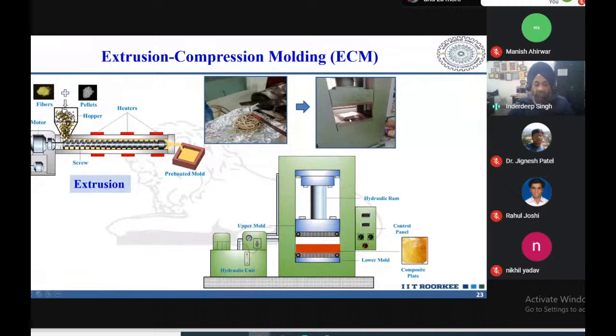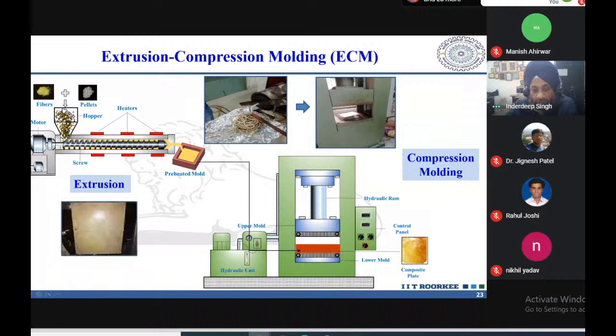So we have designed a mold which can give us a composite plate of 30 centimeters by 30 centimeters, or 300 millimeters by 300 millimeters, and the thickness can be maximum 6 millimeters. That mold we already have for our compression molding machine, and therefore we are able to form composite plates like this, where the fibers are distributed all along the polymer matrix.